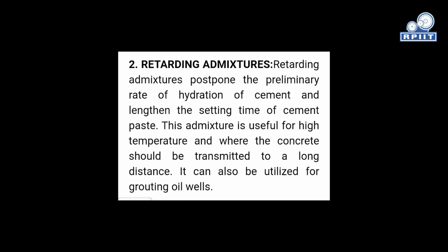Second is retarding admixture. These are the admixtures which are used to postpone the preliminary rate of hydration of cement and lengthen the setting time of cement paste. And this admixture is useful for higher temperatures and where concrete should be transported over a long distance, and it is utilized for grouting oil wells.